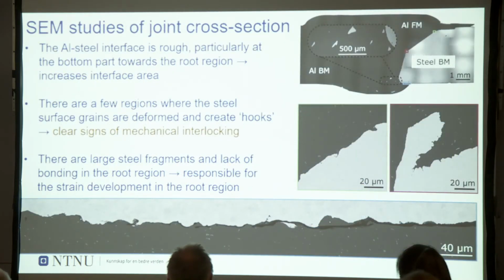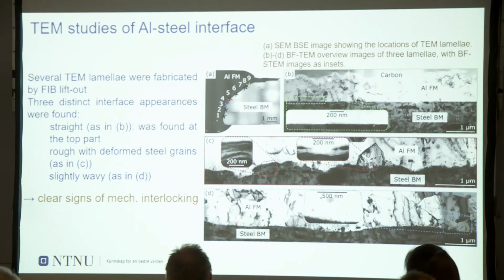Another interesting observation is that if you study the SEM surface of the aluminum steel weldments, it is evident that we have a clear sign of mechanical interlocking at a smaller scale. And this is one of the most important effects for the fatigue purpose that I would like to discuss with you later. If you go down to the TEM studies of the aluminum steel interface, we still have clear signs of mechanical interlockings. We have investigated different points of the weldments, and in any points where the bonding was fine, we have found the mechanical interlocking in the structures.